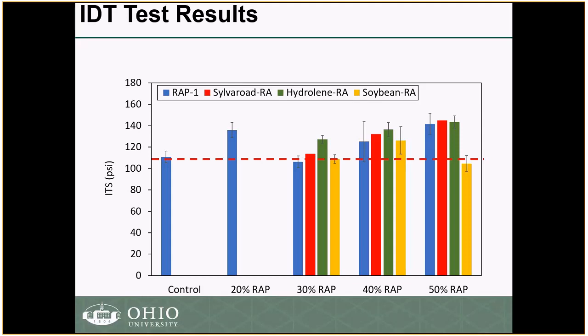The IDT test results: for the same virgin asphalt binder, if you are increasing the RAP content, you can see that the indirect tensile strength increases. So for example, for the control and the 20% RAP, where we have 64-22, you can see that the 20% had a higher indirect tensile strength as compared to the control. And once we go to a softer binder, we can see a drop in the ITS, but with increasing the RAP, that drop is decreasing.